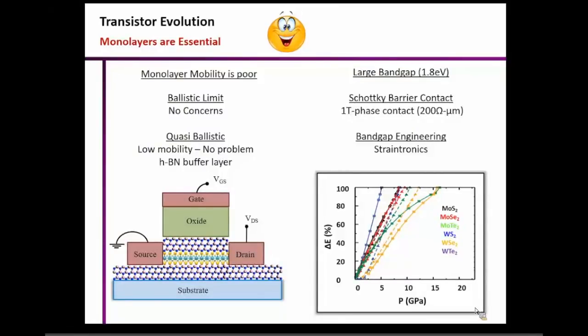With the 2D material, what you can also do is something called strain engineering, which is very regularly done with the silicon technology. Right? With the silicon germanium, you always create the strain to enhance the mobility of your material. You can exactly do the same thing, but when you apply an out-of-plane strain to this 2D material, you can also do band gap engineering. And you can kind of see that by applying different amount of straining, pretty much all the different 2D materials, you can completely collapse the band gap and have semiconductor to metal transition. Okay, so this strain can actually help me to now get to the desired band gap as well.